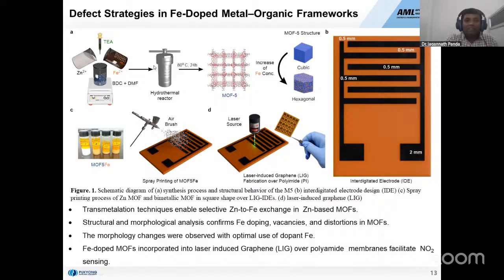So you can see here in the synthesis method, what happens, we took two metal ion solutions, zinc metal ion solution and iron metal ion solution, and we use TEA as a modulator, and we synthesize by the hydrothermal method at 80 degrees for 24 hours. We synthesize the MOF with the defect. So what is the defect here? We are replacing one zinc ion with iron. You can see here, MOF-5, which I already showed in the past slides, shows cubic structures. When we introduce the iron in the structure, it changes to hexagonal, which I proved using FESEM.